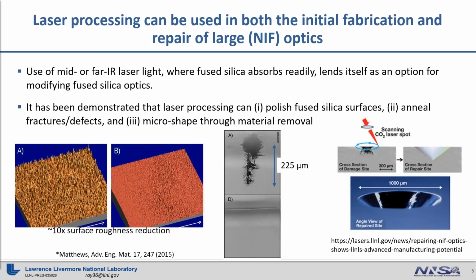Laser processing can actually be used in both the initial fabrication and repair of large NIF optics. If we look at, not the wavelengths that NIF is utilizing, but mid or far infrared, out at those wavelengths, fused silica, which is the material I'm going to be focusing on today, absorbs light, and it gets hot. On the bottom, there have been three demonstrations. On the left figure, you see in the left image a rough fused silica surface. But then panel B is after mid-IR illumination, so a 10x surface roughness reduction.